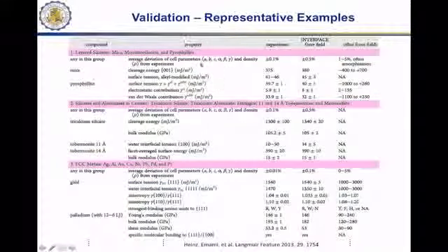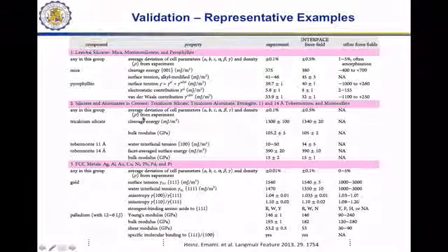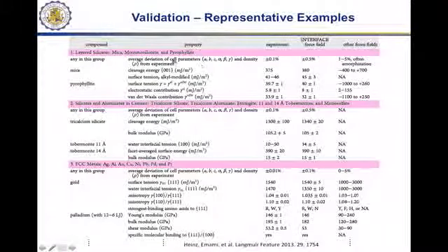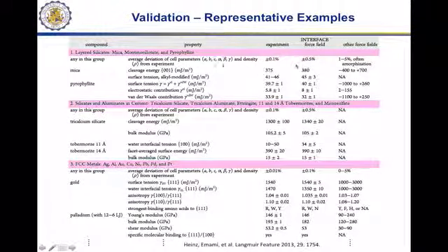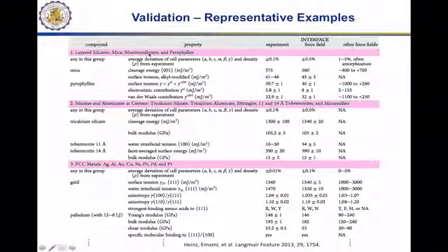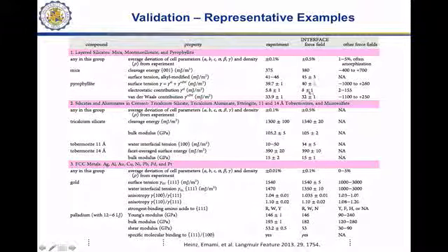Now, what is so particular as an advance in interfacial properties? So this is shown here. It's a very busy slide, basically showing certain types of parameters or properties that we are reproducing very well. Like here, cell parameters, for example, the agreement with the experiment is usually better than 1%, 0.5%. Then cleavage energies and surface tensions, the agreement between experiment and what we see in the interface force field is very good here for several clay minerals.